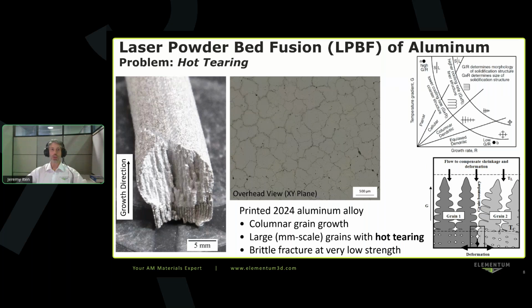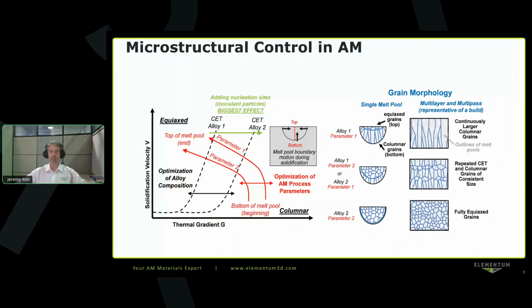So what you need is microstructural control in additive manufacturing to get the properties that you want. Just taking a legacy alloy, printing it doesn't always work. You can control the properties that you get by controlling the columnar to equiax transition during solidification. There's a few ways to go about this. So one of those is you can optimize the alloy that you're working with. You can make small changes to the alloy that can help with changing the transition from columnar to equiax. However, if you're working within a specific alloy system, you only have so much flexibility before you've completely changed your material. And that limited flexibility can make limited changes to your transition from columnar to equiax solidification.